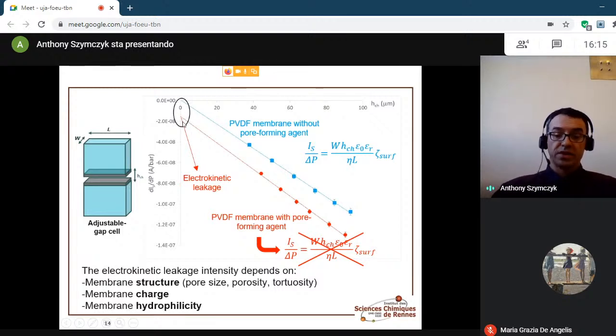As there is no streaming channel when the distance between the samples is zero, this implies that this current is flowing through the bulk of the membranes. This is the electrokinetic leakage phenomenon. Its magnitude is expected to vary with the structural features of the membrane, the pore size, the membrane porosity, and the pore tortuosity. The electrokinetic leakage is also impacted by the membrane charge, since the streaming current results from the motion of the excess of counterions in the electrical double layer, and it also depends on the hydrophilicity or hydrophobicity of the membrane, which make it easier or harder the penetration of the measuring solution in the membrane matrix during the electrokinetic experiment.